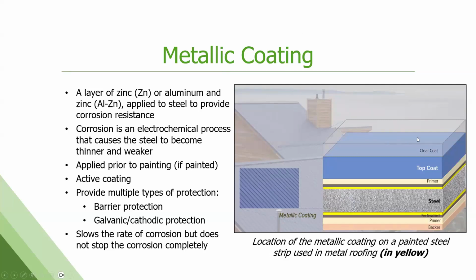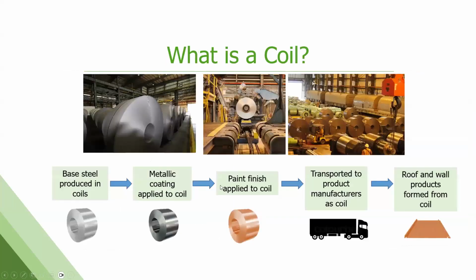This is a mock-up here of a cross-section of a coated steel product. The yellow would represent the metallic coating layer. It's on both sides of the steel, and then this would be a painted product. We would put primer and top coat, maybe a clear coat. These ratios are actually not correct. Each of these layers is about the same thickness. It's very, very thin. Each layer is thinner than paper when it's finalized.